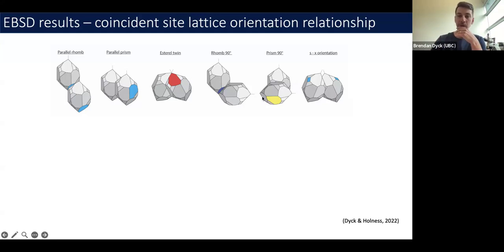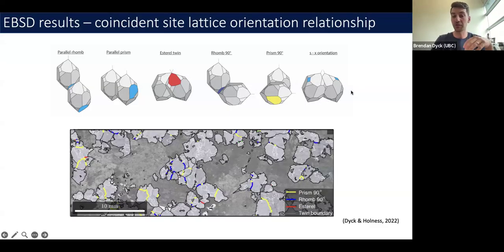Now, using the colors that I've put on this example here with the quartz, we can then color code all the quartz grain boundaries that align with one of these orientation relationships. And what's now very immediate looking at this EBSD data is that the majority of grain boundaries that make up these glomerocrysts, or these crystal clusters, are one of these low energy orientation relationships, which is telling us that low energy configuration has an impact on how these clusters form.